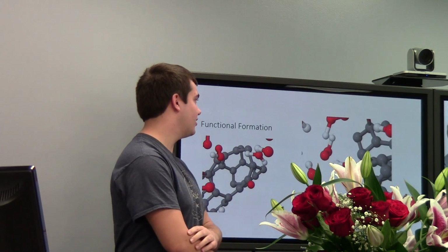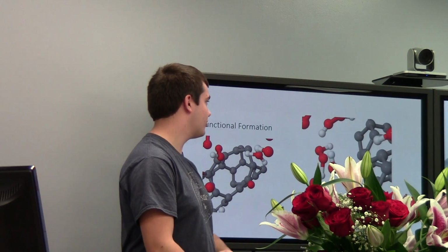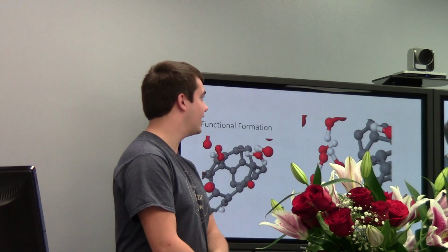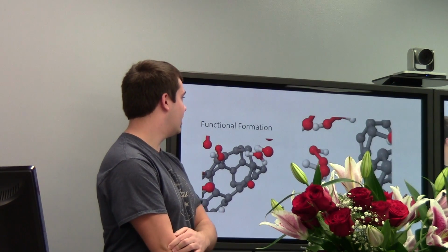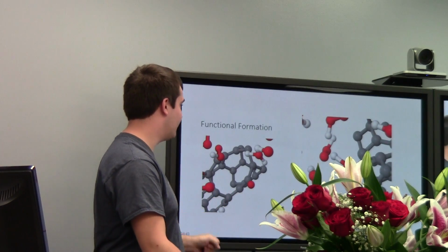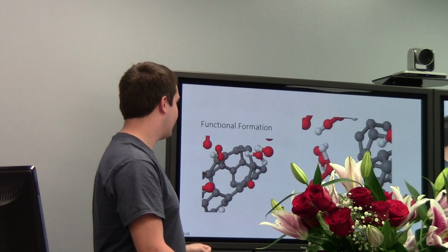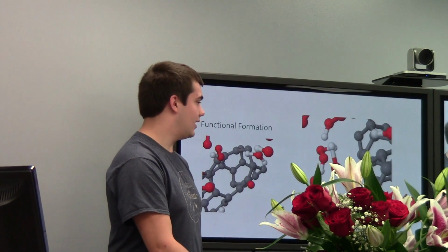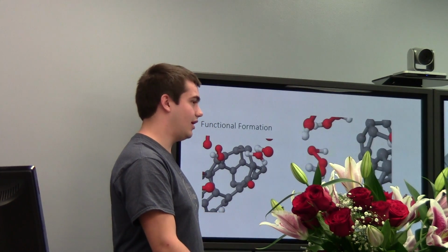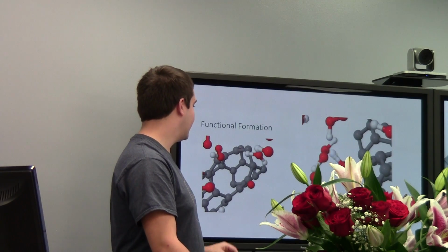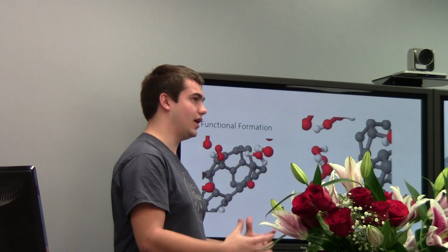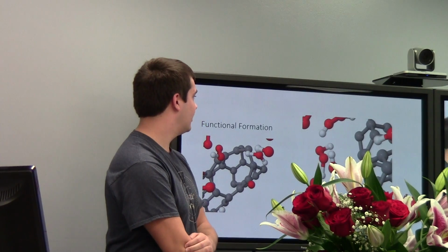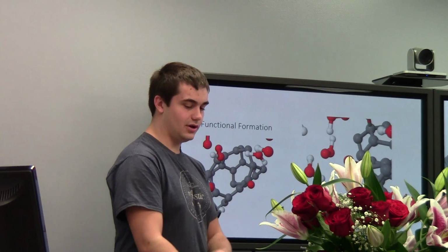The hydrogen peroxide breaks and a hydroxyl group goes and forms with the nanotube, which is one of them that I did not expect to happen. And in this still frame here, it's kind of hard to see, but the 6-member ring on the carbon nanotube was functionalized with 3 different oxygens, and it actually broke and created a hole on the nanotube without dissociating a carbon off of the nanotube.